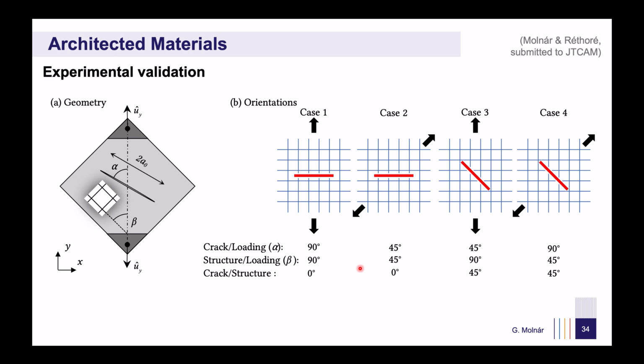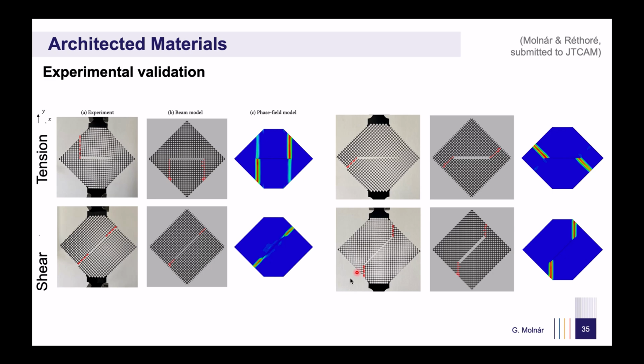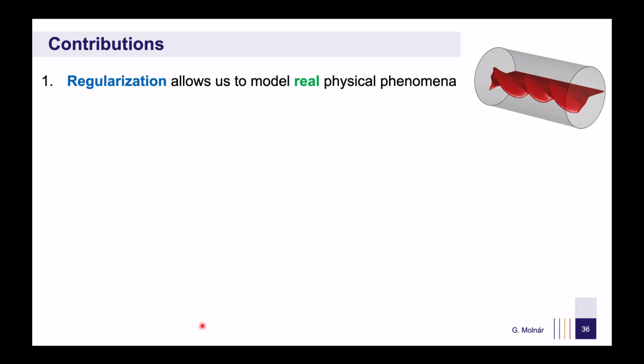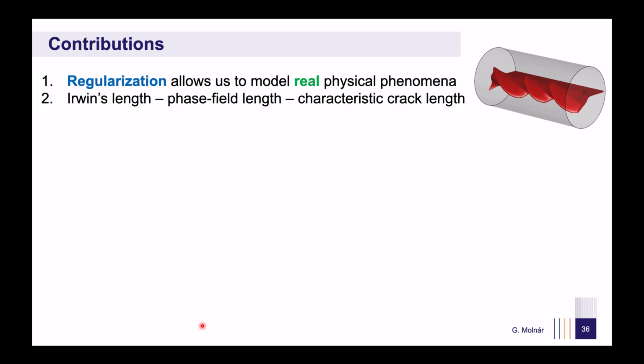Comparing our simulation results to experimental observations, we found excellent correspondence between both models and real-world fracture behavior. In conclusion, this work demonstrates that although regularization length was introduced as a numerical aid, it plays a fundamental role in modeling and understanding complex fracture phenomena. We showed that different length scales arise naturally as a function of geometry and loading, and that these instabilities are not necessarily equal to the length scale used in phase field models.